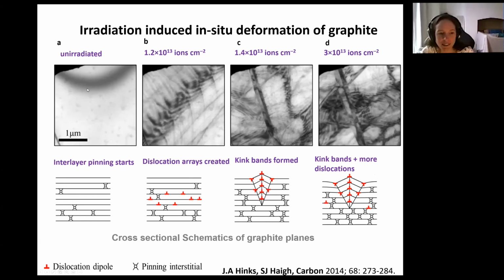So we start with an unirradiated specimen which has this line defect in the original system. We then get rows and rows of dislocation lines, and then those dislocation lines agglomerate to produce this very, very prominent line defect. We also can see there are actually similar defects happening at 60 degrees, which are accommodating effectively. You can imagine it's shrinking in all directions. So we need line defects in all directions to accommodate that 2D shrinkage. And what's happening here is that in order to preserve the stacking of the system, which is the most stable state for these crystals, the dislocations reach a certain density and then want to line up. So we're lining up the dislocations into particular grain boundaries separated by regions of perfect stacking.